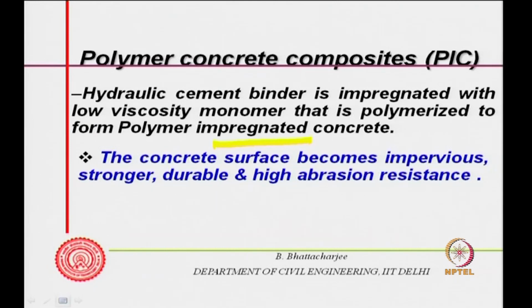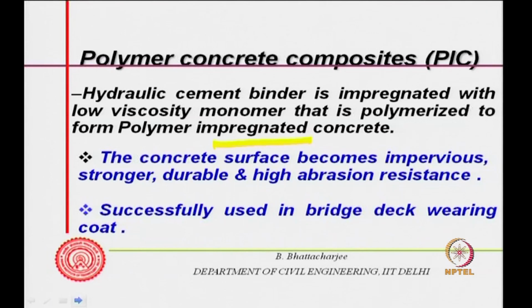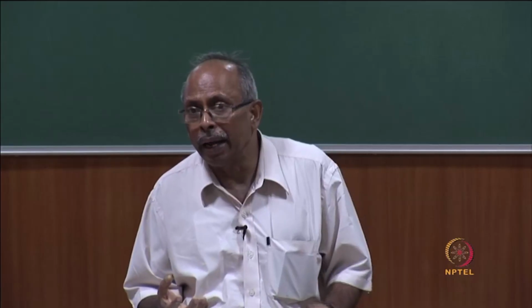The strength improvement ratio can be as good as 2 in this kind of material when tested in laboratory cylinders, and it is successfully used in bridge deck wearing coats, because wearing coats tend to get damaged and distressed because of abrasion from the wheels and so on.